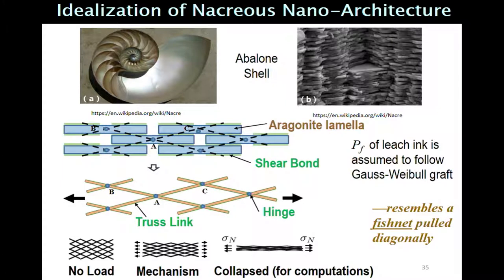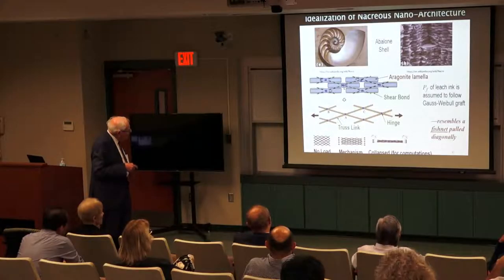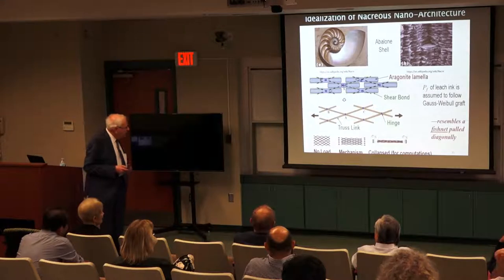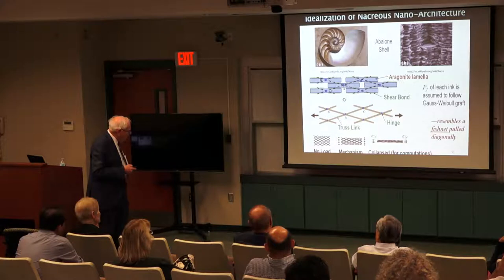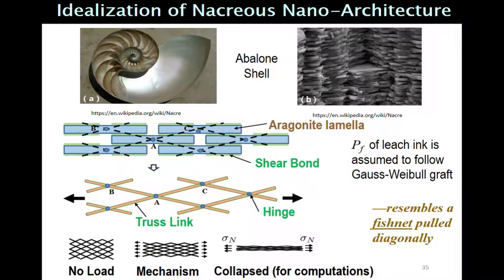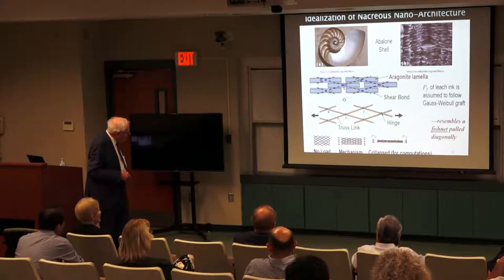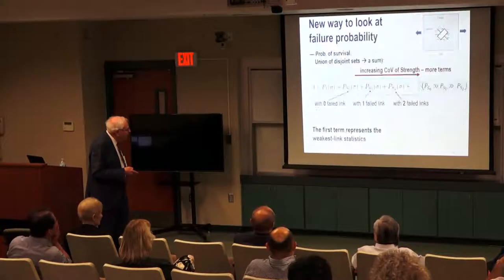So we have rigid elements, and under longitudinal loading, which is what is of interest here, not transverse loading, you have to transmit the force by shear from this platelet to this platelet, and then to this. So the force transmission looks like this, and it looks like a fishnet pulled diagonally. Now the question is, it can be solved, and it can also be easily simulated. My student runs millions of simulations. We use MATLAB, we use the program for a truss. Initially we propped it so it does not collapse, but it makes no difference statistically. We let it collapse to a line, but this connectivity is there, and that's how we obtain the results.